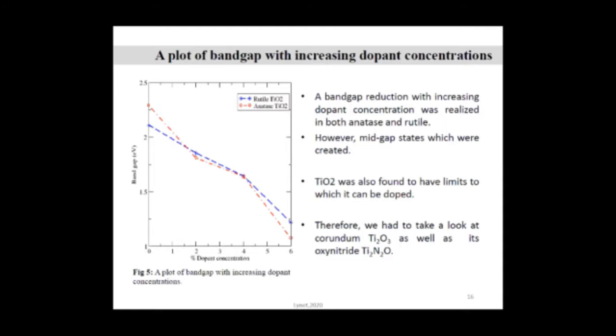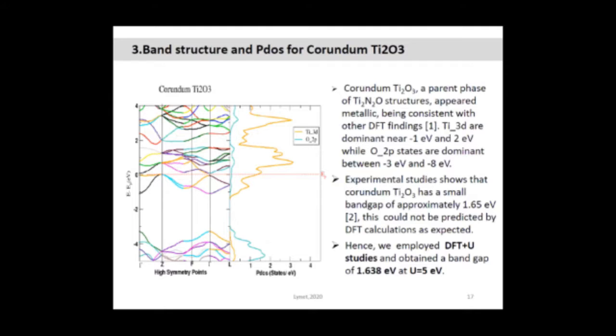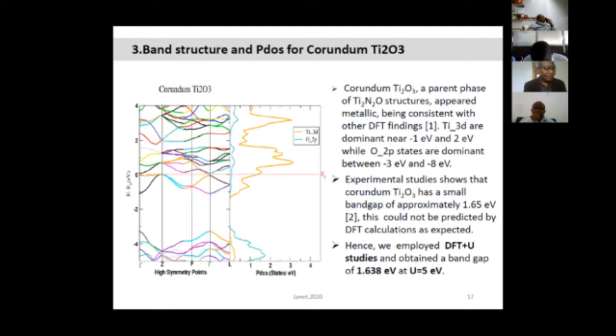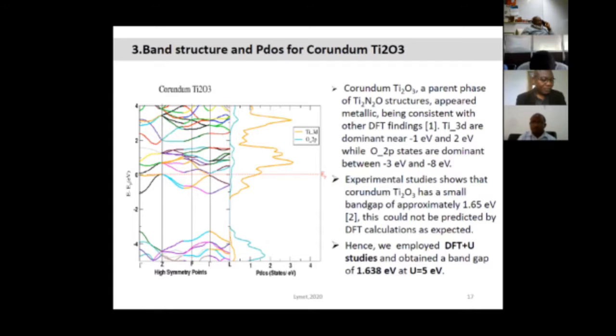So we did the electronic property and band gap calculations for corundum Ti2O3, the parent base of the titanium oxynitride, which appeared metallic. We can see the position of the Fermi level, the red line. It appears to be metallic. This was not a unique finding from us; it is consistent with other DFT findings. However, this material has been reported experimentally to be a semiconductor. So we had to employ DFT plus U, which is known to correct the band gap of materials, to try and get a more relevant band gap of this material.